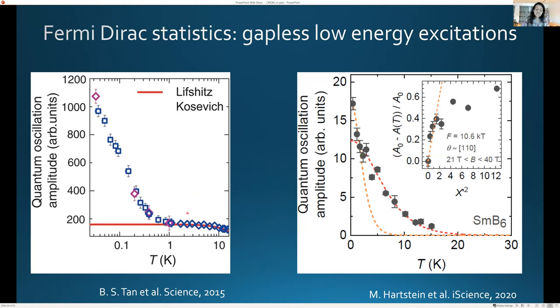So in this case, actually two things happen. If I look at high temperatures, the oscillations definitely keep growing. But when we go down to the millikelvin range, they start growing even more rapidly. So this is a log, this is a linear scale. The oscillations grow Lifshitz-Kosevich-like down to about 1 Kelvin, and then below that, they start growing even more rapidly. They certainly don't flatten or decrease. And so this is just showing the extent of growth. If I benchmark it to the lowest temperature, you can see there's a rapid growth at low temperatures.